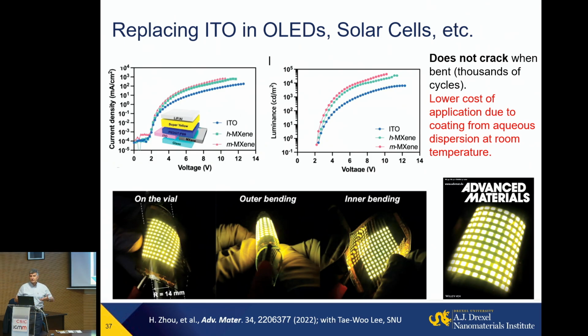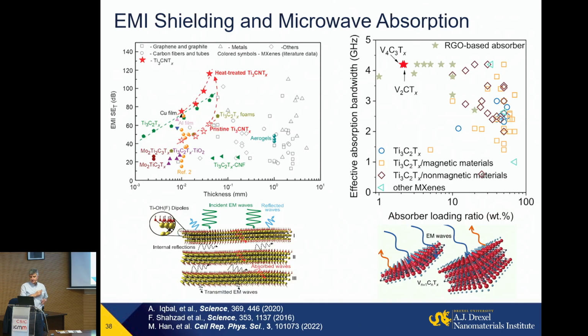This is just another example of combining metallic conductivity, transparency, and tunable work function. Work with a Korean collaborator, Seoul National University, Tae-Woo Lee. They used MXene to replace ITO. The initial idea was simply they wanted to make LEDs bendable, and now they can also make them foldable and stretchable even with MXene. But because they were able to better match the work function compared to ITO, it not only prevented cracking when bent, but luminance increased by an order of magnitude, so they became about an order of magnitude brighter compared to the same devices using the traditional transparent conductor indium tin oxide.